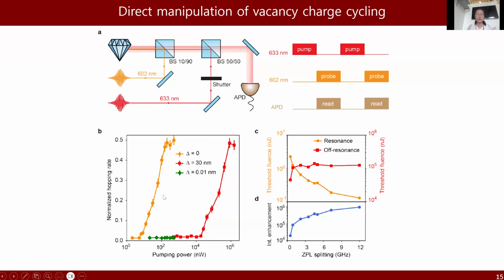From the lower left figure, we can see that for the resonant pump, a few nanowatts is required for driving this charge cycling, but for off-resonant pump, tens of microwatt is required. Here I want to emphasize that the off-resonant pump requires both 1,000 times larger pumping power and 1,000 times longer illumination duration to achieve the same driving efficiency as resonant pump. That's why we use threshold fluence, which is defined as the threshold power times the illumination duration, to compare the resonant pump and off-resonant pump.